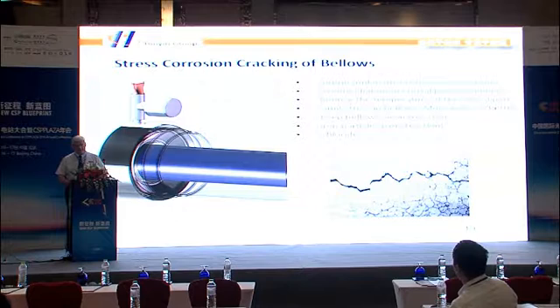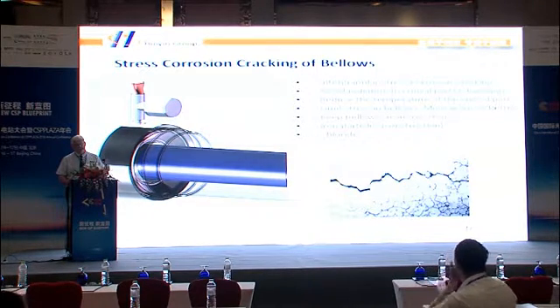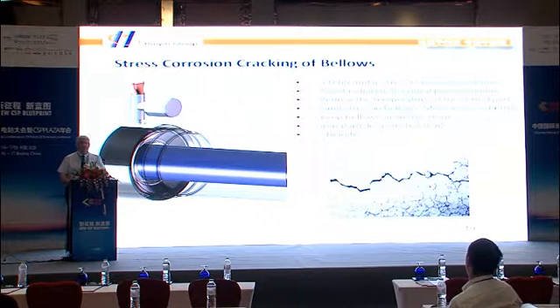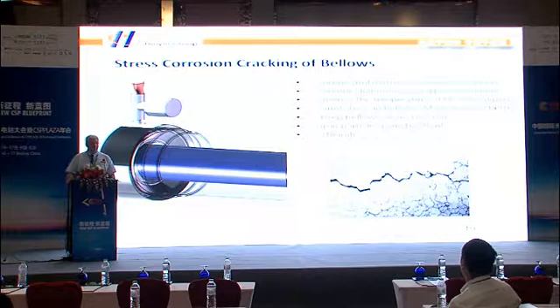Stress corrosion cracking is another thing in the bellows. It happens when stainless steel is exposed to high temperatures above 420 degrees. At that moment, carbon is pushed out of the cells and can combine with the chromium that is protecting the grain. If that happens, you can get stress corrosion cracking. And this has been a failure mechanism that has occurred quite often in these types of receiver tubes.